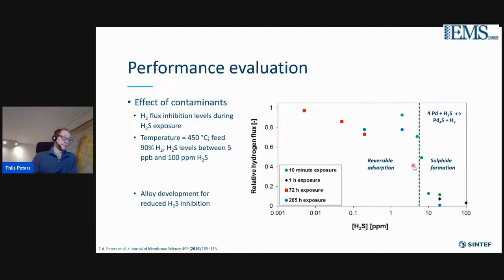While if the membrane is exposed to a lower concentration of H2S, so low in the ppm or even as low as the ppb level, the flux is inhibited, but it can still be completely reversible. This was done for palladium silver membranes, but you could reduce the H2S inhibition by proper alloying, for example, with gold.